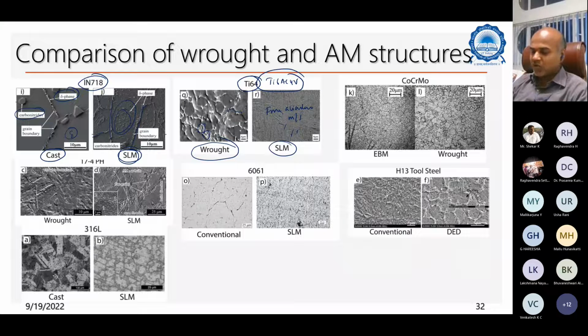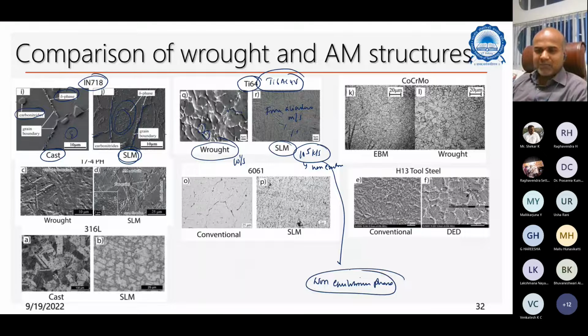What happens is that because of the rapid cooling rates, you're talking about 10 power 5 K per second, because of this you actually create some kind of non-equilibrium phases, which is sometimes beneficial for the strength, but very bad news for ductility or toughness. Okay. And this again is the cobalt chromium moly, which is also an alloy that is made by both EBM additive manufacturing and the wrought process. In the wrought process, you see a slightly bigger grain size than the EBM processed cobalt chrome moly, and the grains are very small, very fine.